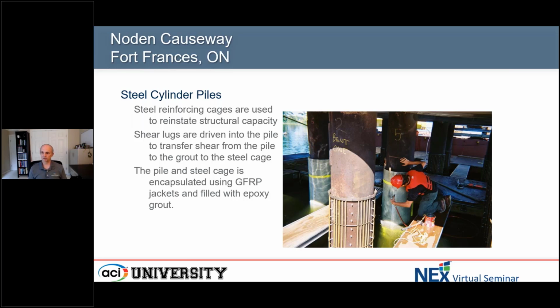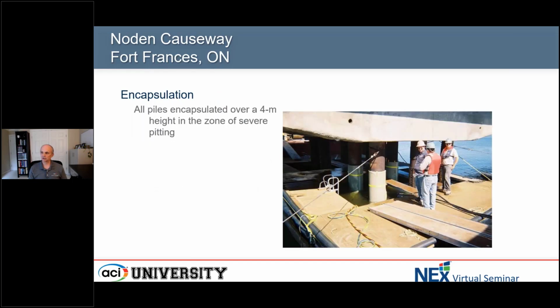There's that steel cage with periodic shear studs that are going through it. And then the gentleman back behind there is installing a fiberglass jacket around that steel cage and those shear lugs. And then that ultimately gets filled with an epoxy grout, in this case, to fill that encapsulated pile. So you can see that in the photo there, some of the grout just coming up out of the top of that encapsulation. A lot of these were originally done just in that splash zone, which was about a 4-meter height of very severe pitting corrosion. Ultimately, a lot of these were encapsulated, though, full height.